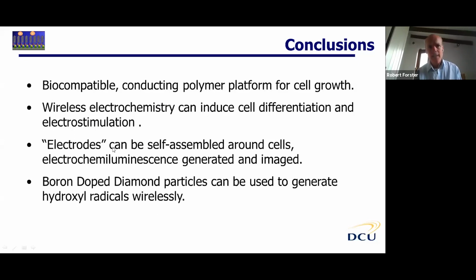We think we can begin to contemplate the possibility of self-assembling, in situ within biosystems, electrodes that we can address wirelessly and, for example, generate electrochemiluminescence. These boron-doped diamond particles seem to be quite efficient at generating hydroxyl radicals so that we can decompose water in a wireless way.